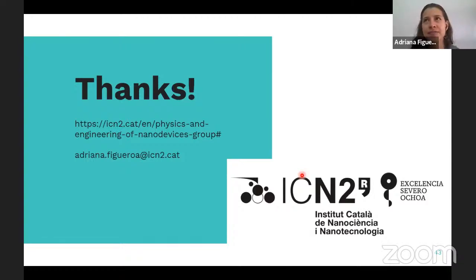Yeah, definitely. Despite the fact that we don't use the same substrate to grow the bismuth selenide, we compare, and the growth orientation is the same. It's the same 111 that we use. We compared our images with theirs, and they're basically the same. Structurally, they are comparable layers and interfaces. So that's why we are very surprised not to see an XMCD signal on those interfaces. But yeah, I agree with her point about having a different orientation, and that could affect the observation of proximity effects. But we made sure that we follow the same recipe and that we have structurally comparable layers. Thank you.